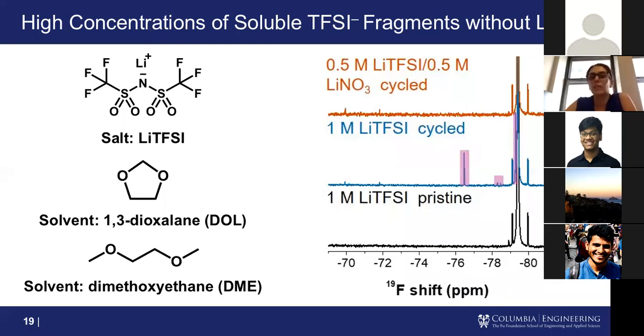However, if we take a look at the fluorine spectra, where we only have fluorine on our salt here, so our TFSI has these CF3 groups on either side, we do see differences in our salt decomposition when we have lithium nitrate present versus when we do not. So this is the spectral signature that we get for TFSI, just in its original state.